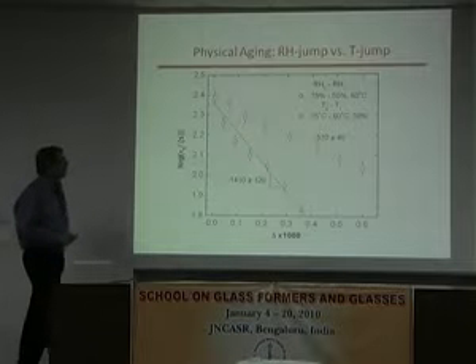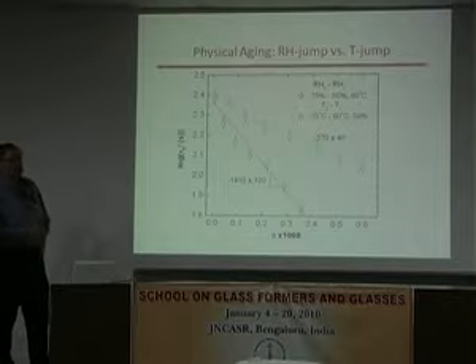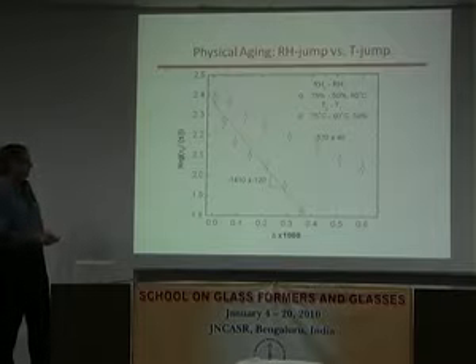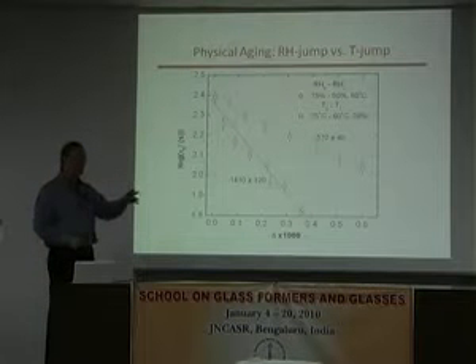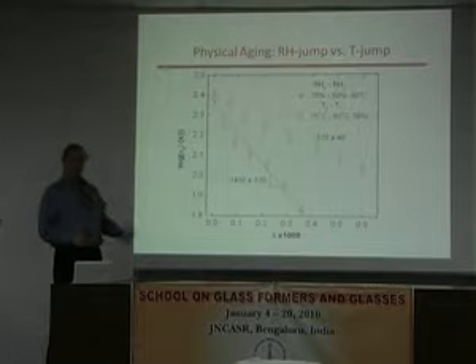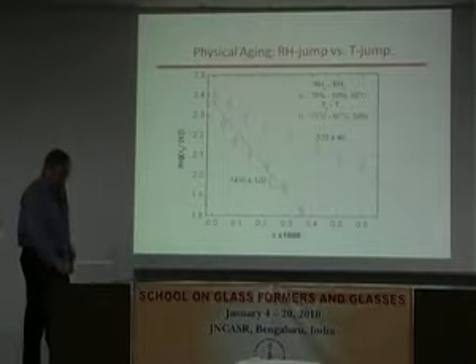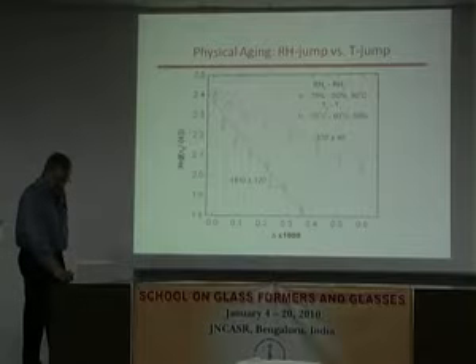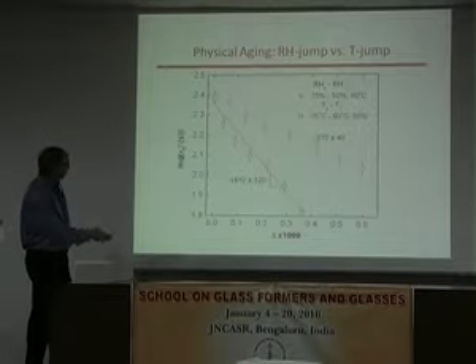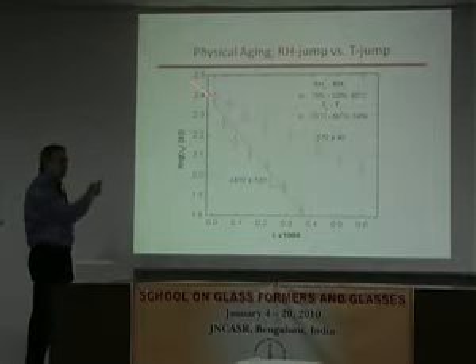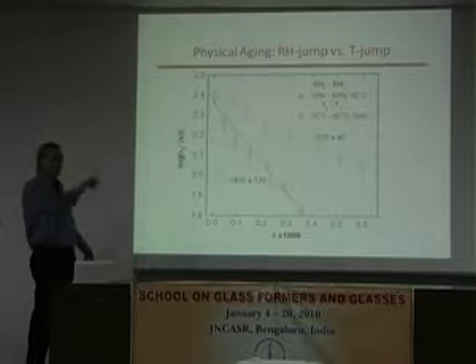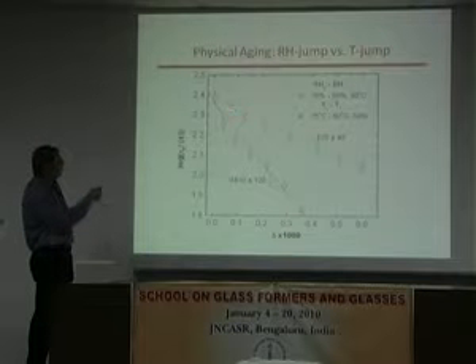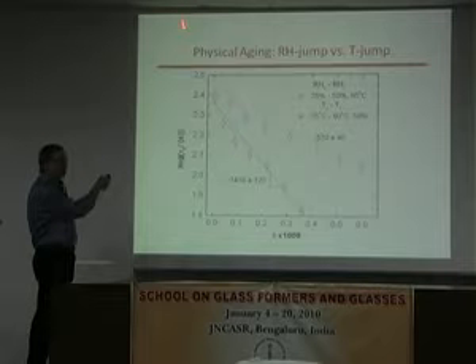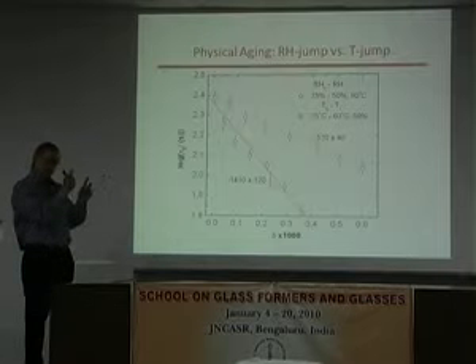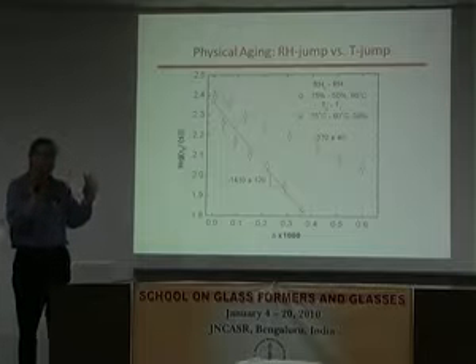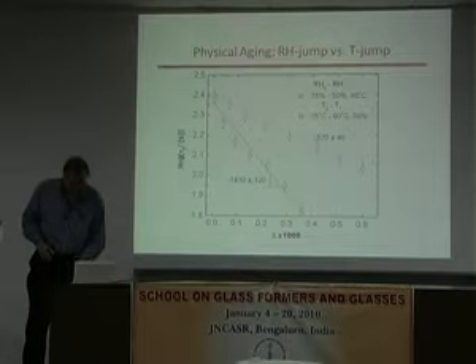Well, it depends on the choice of the condition. Because the humidity jump, they were like a factor of 6 different, right? So it's going to depend on the details. Now, one thing is that these go through 0, so they cross. So when I have a negative volume, then the humidity jump is relaxing faster than the temperature jump. So there's a cross in behavior, which we really don't understand. I think it's something that needs to be worked on more.